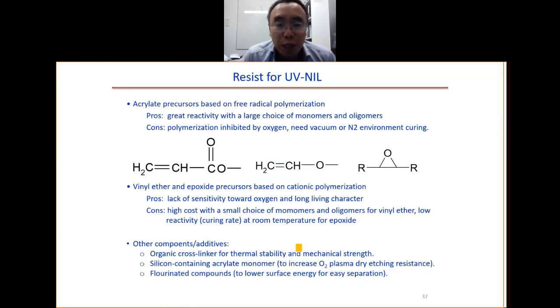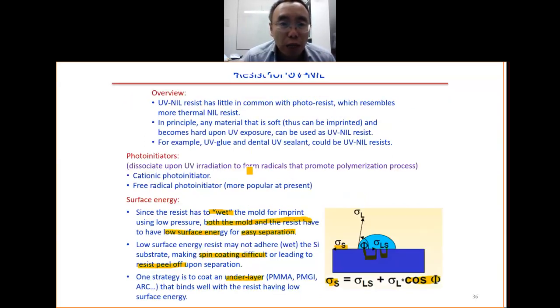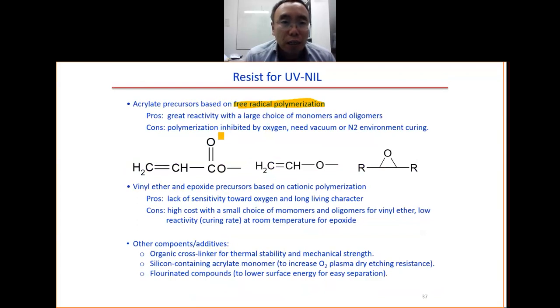Here are examples of the UV imprint resist. We have two types: free radical and cationic photoinitiator. The first one is based on free radical polymerization. For this one we can use the acrylate precursor. It has great reactivity, which means a higher curing rate, with a large choice of monomers and oligomers. The problem is that this free radical polymerization is inhibited by oxygen. So we have to do the lithography in a vacuum, in a nitrogen environment, or somehow use the soft mold to drive the air out before we do the imprint.